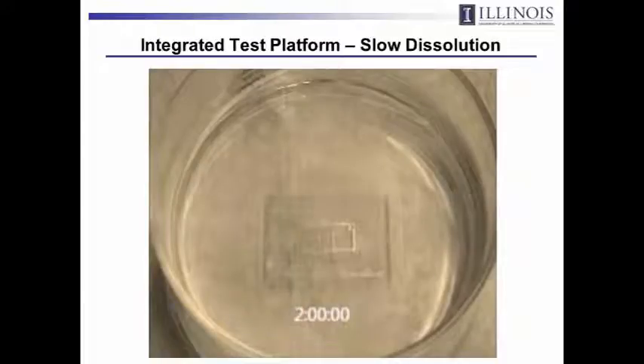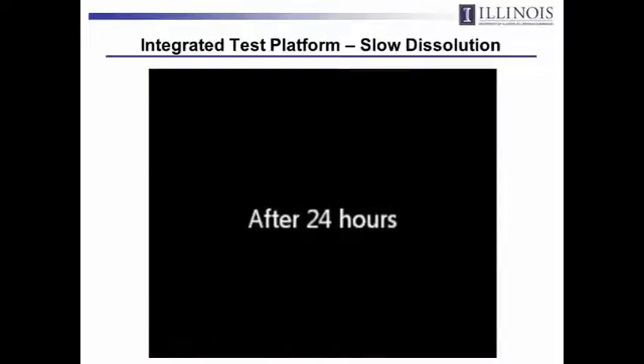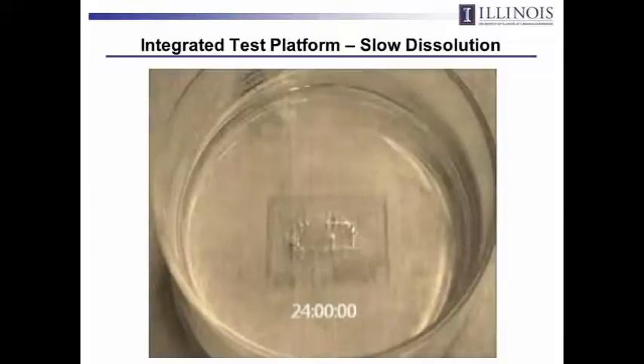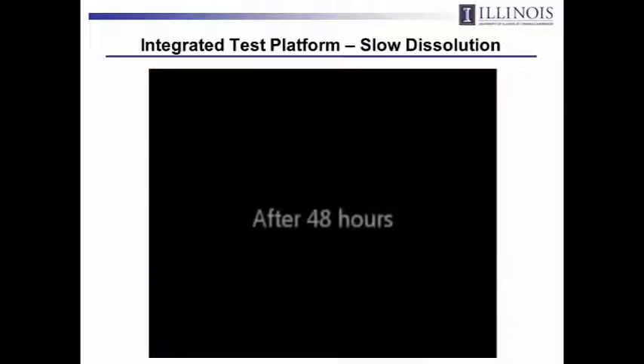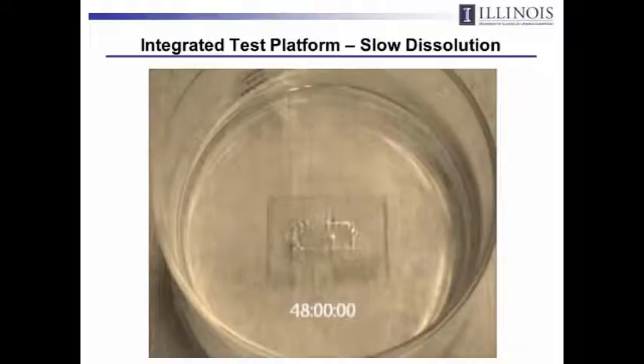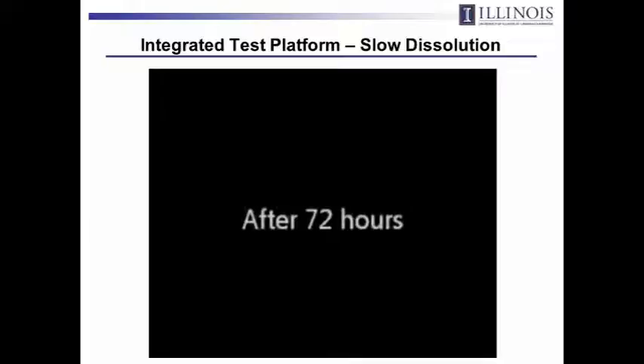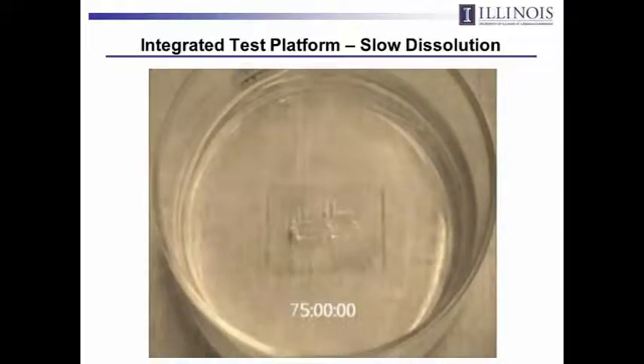So here's an example. We've used silk, in this case treated so it's very crystalline, so its rate of dissolution in water is very slow, and it's sealing the circuit away from the water, so the circuit doesn't dissolve either. It's a little bit hard to see with this light. You see a little bit of wrinkles here. That's because the silk is swelling a little bit, but it's not dissolving away, and the circuit is still functional, and it still remains.